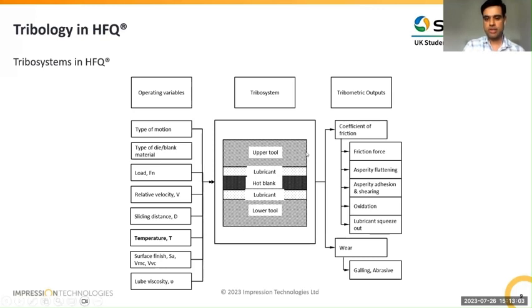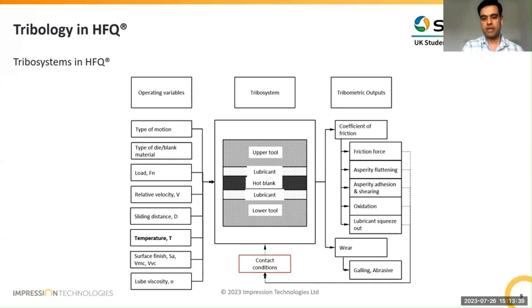And the tribometric output, essentially what we all measure in tribology across the different fields, is coefficient of friction and wear. But the friction coefficient is a function of the friction force, which is in turn a function of asperity flattening, adhesion, and shearing. Because we are looking at a high temperature contact, there's oxidation both on the steel, on the lubricant, and on the aluminum blank. And there's also some dynamic effect to lubricants, such as squeezing out of the contact. And all these aspects together influence the contact conditions. And after we start pressing one part to the other, the entire tribo system is then developing. So it's a rather dynamic nature of the tribo system that we encounter in sheet metal forming.